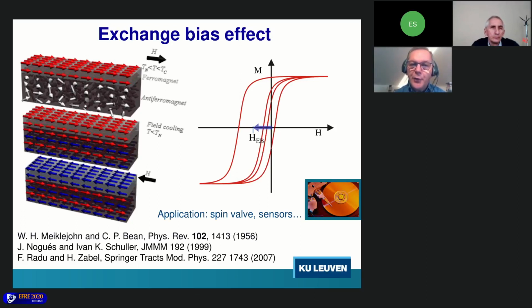But it becomes interesting when you take this system and cool it below the Néel temperature of the antiferromagnet, because then you will also establish antiferromagnetic order in the cobalt oxide layer.